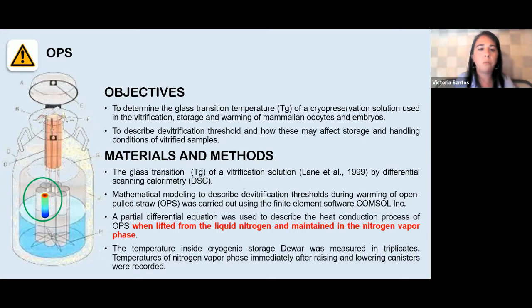How did we do this? Well, we first measured the Tg using differential scanning calorimetry. And we used mathematical modeling to predict the time-temperature curves and the devitrification threshold during warming of OPS. This was done using the numerical method called the finite element technique. And we did it in a software called COMSOL Multiphysics.